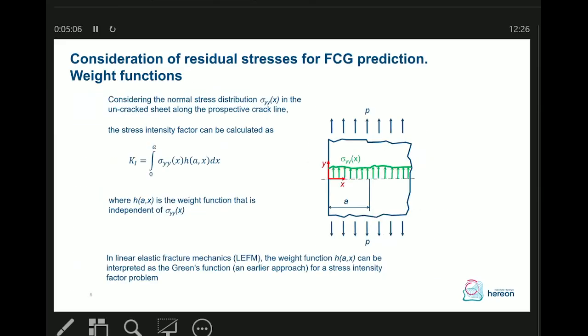The concept is in principle simple. In linear elastic fracture mechanics, the weight function can be interpreted as a Green's function in a linear approach for a stress intensity factor problem. If you know, for example, the residual stress profile in the specimen, using integration we can calculate the stress intensity factor due to the presence of residual stresses.